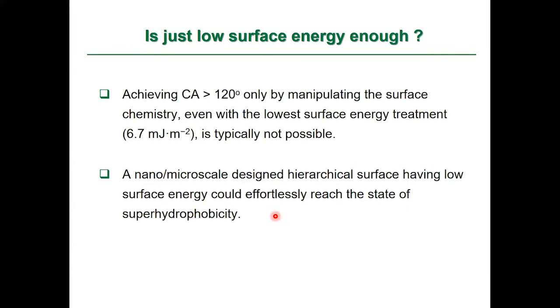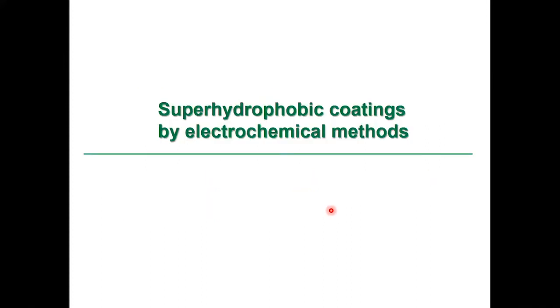Is just a low surface energy enough? We saw that superhydrophobicity can be achieved maybe even only by the hierarchical surface structuring, but achieving a contact angle greater than 120 only by manipulating the surface chemistry. That means even if we use the lowest surface energy treatment, we cannot achieve superhydrophobicity on a plane surface. We need a nano micro scale design hierarchical surface. That is the most easy way to achieve superhydrophobicity.